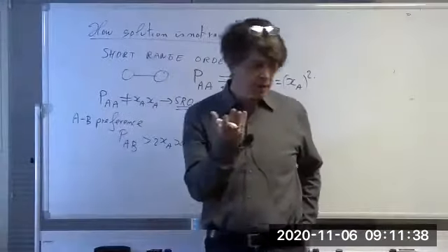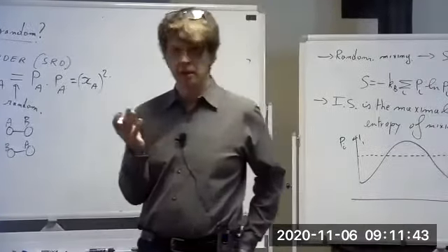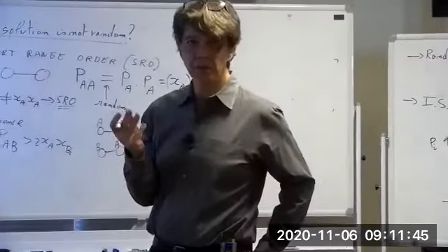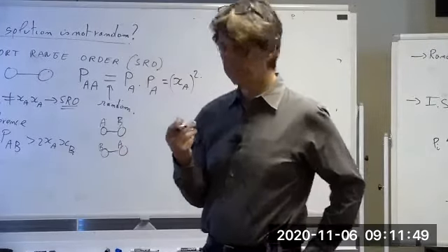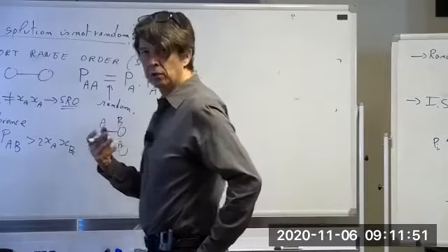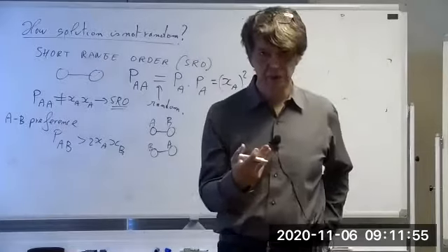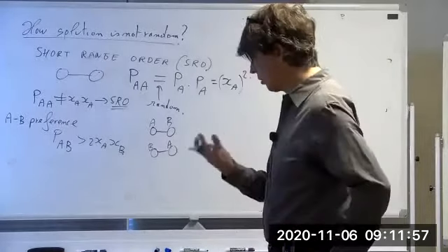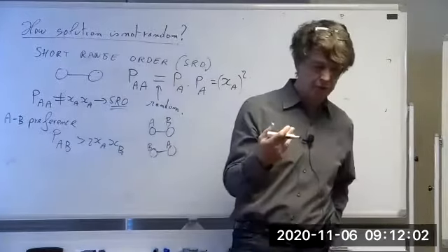Short range order is real. It's actually present everywhere. Most people just don't pay attention to it because it's harder to measure. It is statistical in nature. It does not break symmetry, so you cannot see it in diffraction easily. It has no symmetry breaking. It's been known since the 1950s and 60s. It was totally forgotten and it's kind of on a resurgence now.